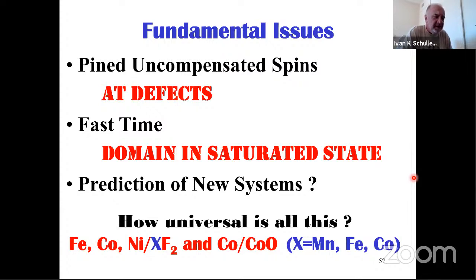The point that I was trying to make here is that the exchange bias in this system that we are working on is very, very big. You have to be a little bit careful: if you look at exchange bias where the shift of the hysteresis loop is much, much smaller than the coercive field, that has all kinds of problems. In these particular systems that I showed you, the exchange bias is much bigger than the coercive field. So clearly there is an exchange bias. Many of the core shell structures have a very small exchange bias, but there is a lot of work on that. So those names, these people in Barcelona, you should look at. Jordi Sort is another name that you may want to look for.